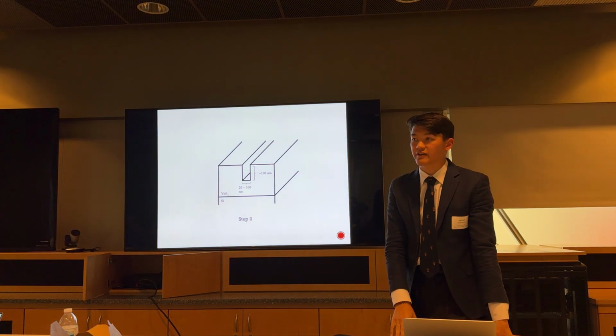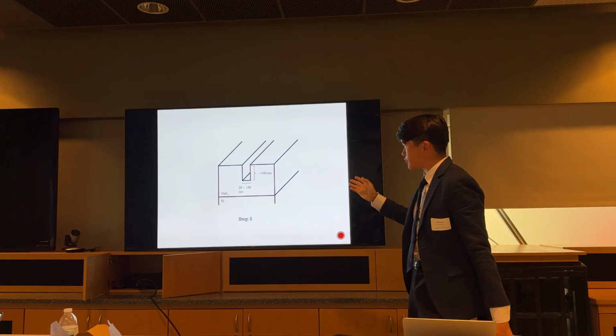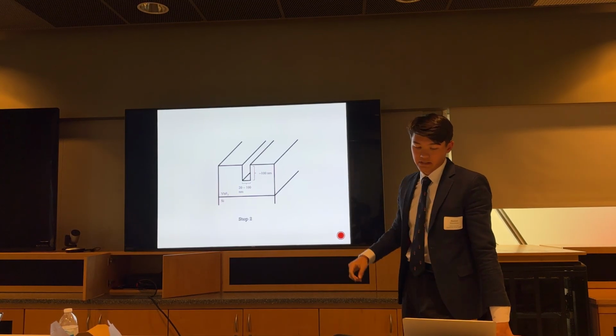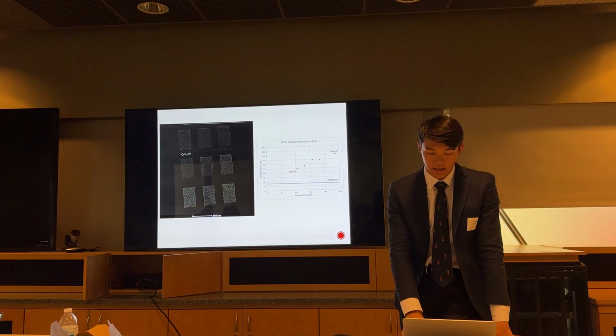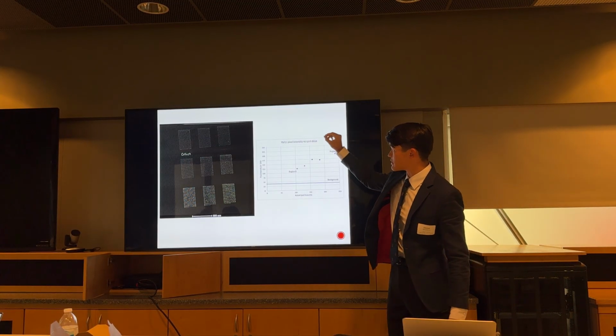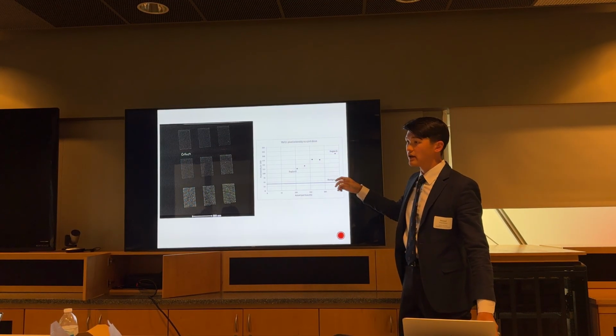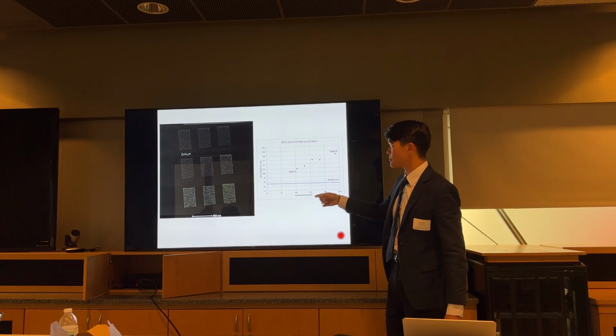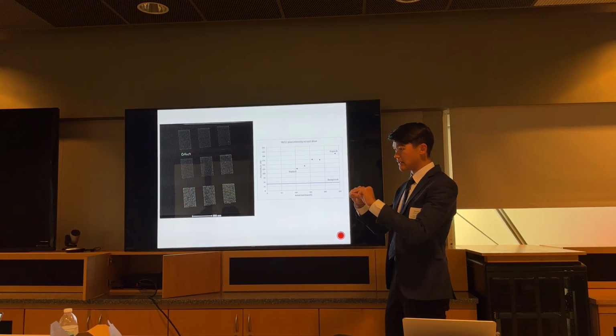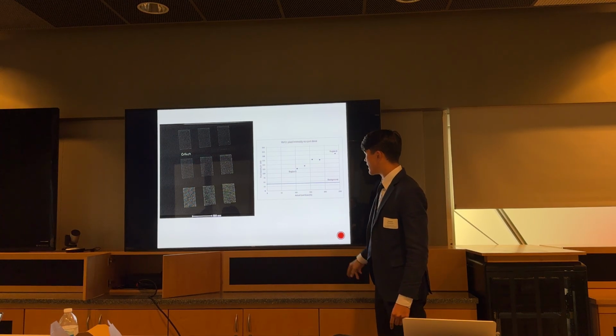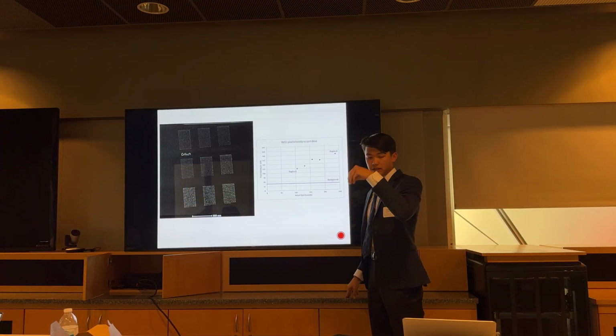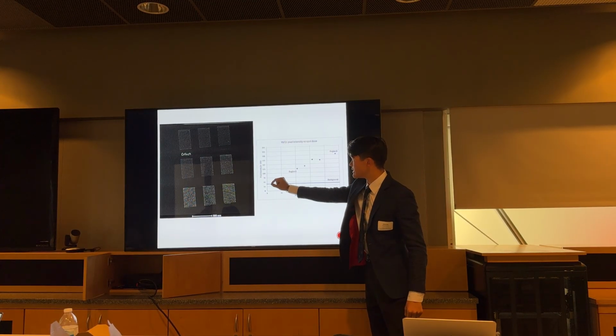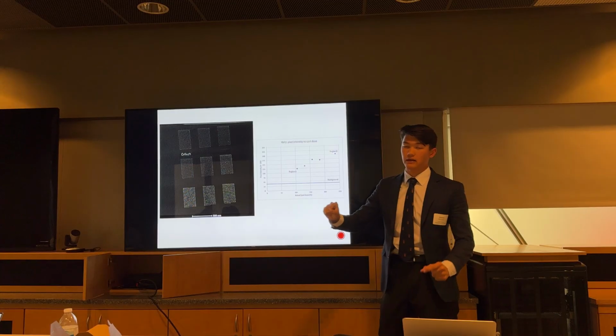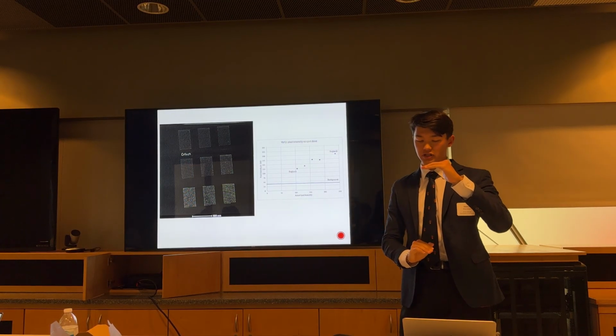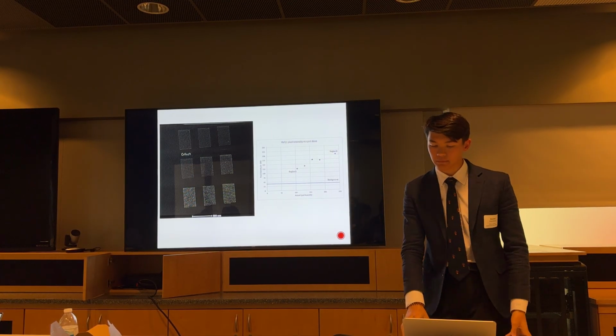Lastly, I assisted Professor Scherer with more fundamental research into the properties of ytterbium fluoride as a self-developing resist. Here is one test where we just expose many different spots on the surface of ytterbium fluoride. This is a transmission electron microscope image, on a very thin layer. We can see that as the dose of the electron beam increases, as you hit it with more charge, the pixel intensity increases, in that the amount of ytterbium fluoride which has been removed increases.